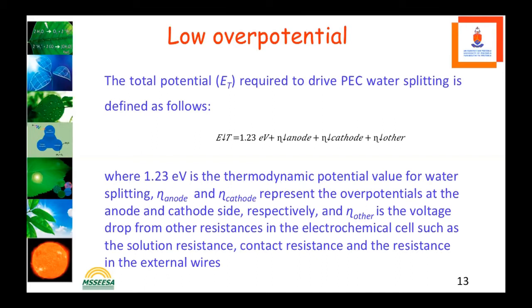What we have done is that we have discovered that if you put the nanostructuring, if you look at the method of preparing your material, then already the method will help you to reduce the external resistances. You know that in a normal diode, we have a very important factor called series resistance, and it is there at all times. And how do we reduce the series resistance, the normal series resistance in any diode? It's when we are cleaning the material properly, simple mechanical interactions. The way you interact with the material, it has to be a pure material, number one. When it's a pure material, your resistance will be lower.